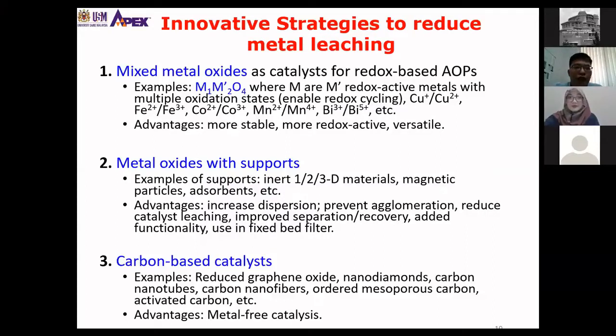First is to use mixed metal oxides. So if you look at just now, the example that I present is on using cobalt oxide. So cobalt oxide by itself is a single metal oxide catalyst. So if we use a mixed metal oxide catalyst, which means we combine this cobalt with another transition metal, let's say we want to make it into a spinel structure, cobalt ferrite, CoFe2O4. So this is an example of mixed metal oxide. And this cobalt ferrite can have a better functionality compared to the original single metal oxide, in the sense that it will provide more stable, more redox active and versatile structure.